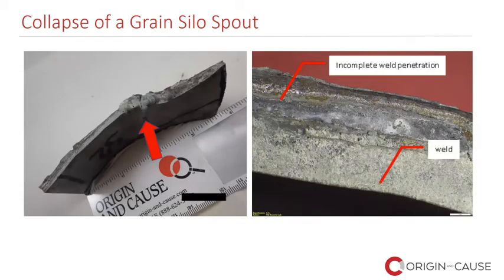As I mentioned earlier, we selected a few weld samples for examination, and one can see with the naked eye there are some problems here. The red arrow points to a large bead, excessive weld bead actually, and the images taken at a low power microscope show that the weld did not penetrate throughout the entire wall. So the weld exhibits a deficiency called incomplete weld penetration.